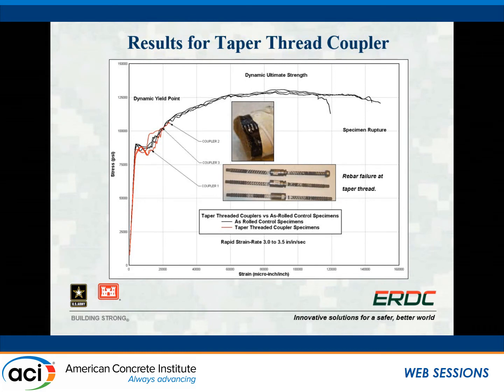It's pretty typical. But in the case of this tapered thread coupler, we can see pretty significant reductions in ultimate strength. The ultimate strength in these bars is around 130 KSI, and it reduces in this case to around 105 KSI. You also get some pretty significant reductions in ductility, from 12-14% down to less than 3%. I also wanted to note how most of these failures are associated with the coupler, with threads in the coupler initiating fracture.